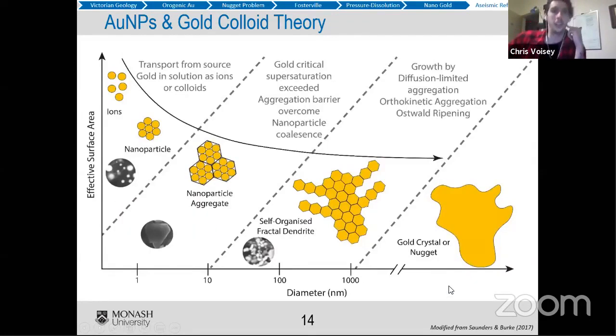So this is sort of the lifespan of a gold particle. You could have gold transport in a source as a solution or as ions or as colloids. So you've got to have a source of gold to come from somewhere. And then once gold reaches a critical supersaturation and you overcome what's called its aggregation barrier, you can start to grow nanoparticles. The aggregation barrier is that since nanoparticles are all similarly charged, gold nanoparticles are negatively charged, they tend to repel each other. And if you can overcome this aggregation barrier, you can make them stick together. And at that point, you're building gold nanoparticles to become much larger.